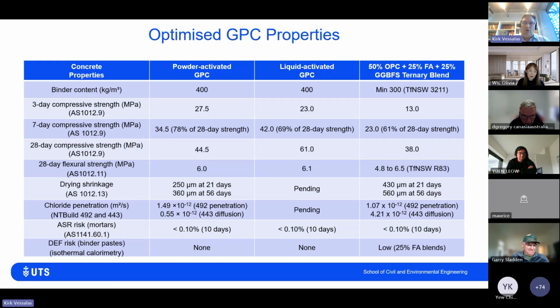So I thought, in terms of results, I'd just end on this particular slide, which gives you an overview of some of the comparative features between a powder-activated geopolymer concrete system that we've trialled at UTS versus a liquid-activated geopolymer system versus a ternary blend. And you can see some of the advantages here highlighted. Much higher 3-day compressive strength compared to a conventional system. We get a much higher 7-day strength compared to the 28-day strength, 78% versus 61%. Much higher strengths around the 28-day compressive strength.